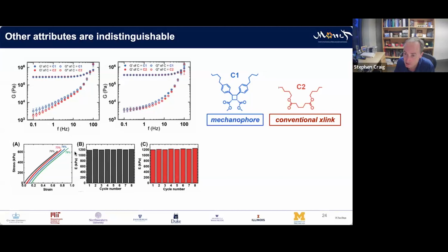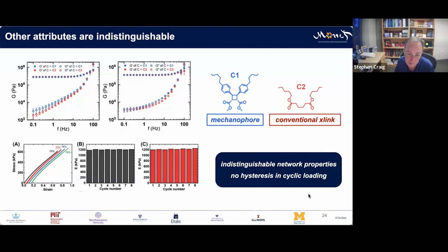At 80% or just a little bit over, that's where the material breaks. So we're going almost up to its limits. This is with the mechanophore, and we can't see any influence from mechanophore breaking. It's very, very small amounts. It has a very minimal impact on properties here. And the conventional control, I will just say, breaks down at around 30% strain, less than half of what we see with the mechanophore. So that's a complete loss of properties where we see absolutely none with the mechanophore here.